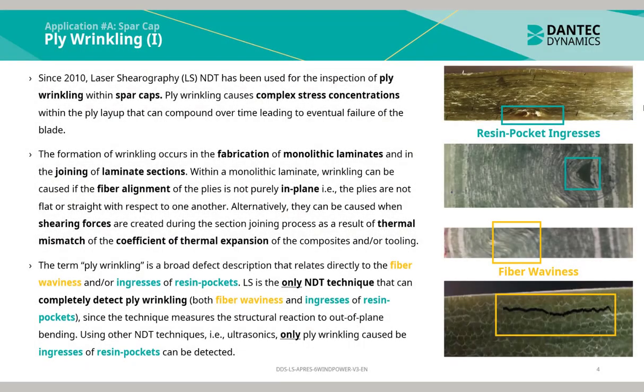Since 2010, laser shearography NDT has been used for the inspection of ply wrinkling within spar caps. Ply wrinkling causes complex stress concentrations within the ply layup that can compound over time, leading to eventual failure of the blade. The formation of wrinkling occurs in the fabrication of monolithic laminates and in the joining of laminate sections.